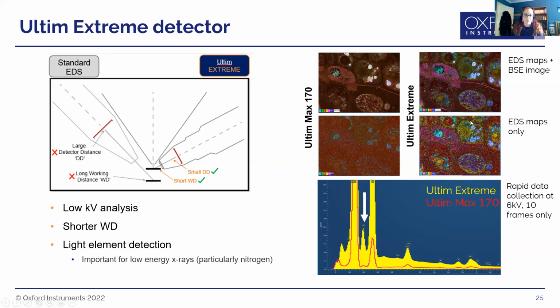And this was only 10 frames, so it's a relatively quick acquisition, hence the data is slightly noisy, but we're getting much better signal out of the Ultim Extreme than we did with the 170. And that is a lot because we're collecting more of the X-ray signal and we're collecting a lot more of those light elements.